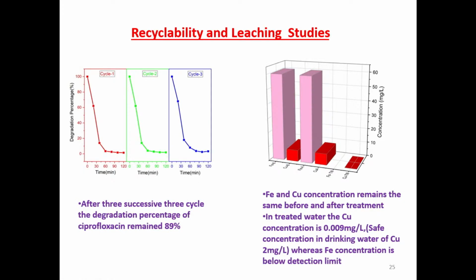Another thing we look forward to is reusing these samples. The recyclability test tells us you can recycle these samples. These are in powder form, and mostly centrifugation is used to take back the powder samples and then reuse them for the next cycles. Recycling up to 3 cycles gives us a degradation rate of 89%. Leaching studies tell us if you have iron or copper leaching in the treated water. As you can see, iron was below the detection limit, and the copper concentration in the treated water is much below the permissible limit in drinking water.